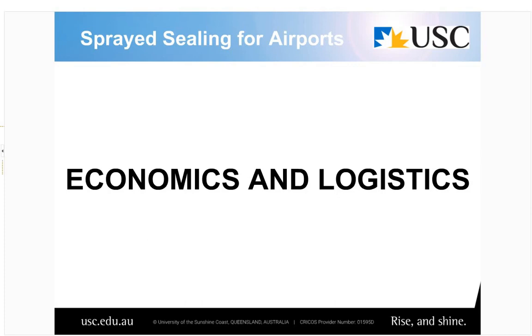sealing really, certainly in my view, I don't know that it was Jim's view or whether it was a question, but my view very strongly is, if your runway is too busy to be sealed by closing it for periods in the day, then it's too busy to be sealed. Because of the visual nature of getting a seal right, and because you're doing the trials, and then you need to continually monitor to make sure that you're still putting an appropriate amount of bitumen and aggregate down in every spray run every day, you can't do those things at night.